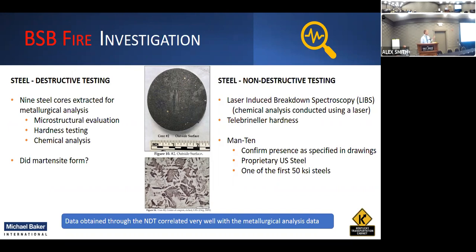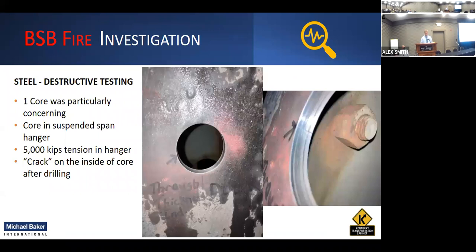In order to look at that, we did some Brinell hardness testing, again, seeing that we had a change in that hardness, as well as they brought out a laser-induced breakdown spectrometer. Essentially, you shoot a laser and they can give you a readout of the chemical composition of the steel to confirm whether we do have this high manganese in it, and if it actually is this Man-Ten steel. All of that was confirmed. So it was some interesting data that we produced off of that.